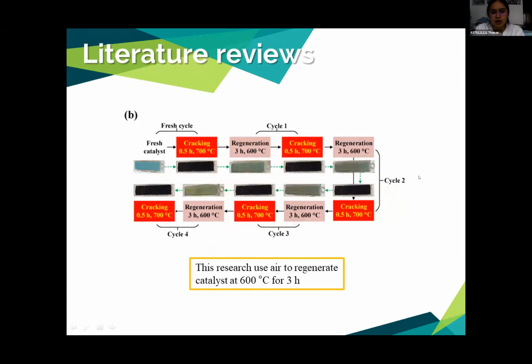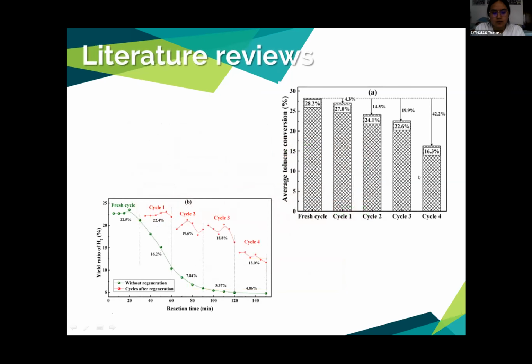And this paper regenerates the catalyst for a full cycle, regenerated by air at 600 degrees Celsius for 3 hours. From the toluene conversion, results show a decrease of conversion when the catalyst is not regenerated. But in the first regeneration cycle, the conversion is 27%, nearly the same as the regenerated catalyst. But in the fourth cycle, the conversion dropped to 16.3%.